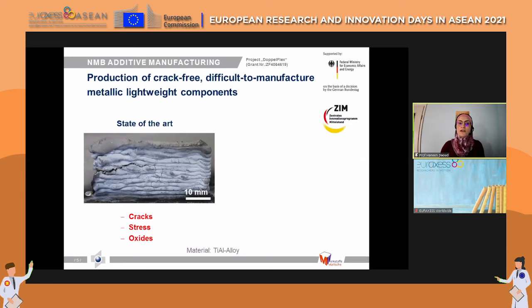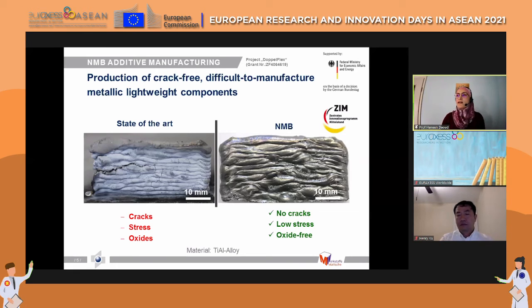That is state of the art, a printed component or a part made from titanium alloy. You can see that there is a lot of oxide, and also you will have stresses and cracks in the whole part. By using our self-developed process, you will not have any more cracks, and the oxide will be eliminated. And this is the benefit from this process.